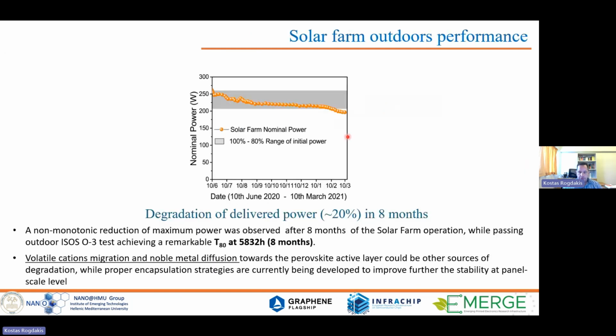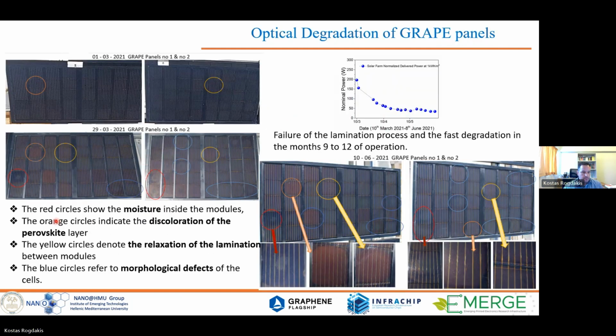But after this period, we recorded some visual degradation effects in our panels. You can see these regions here that are reddish, that correspond to some degradation effects, either coming from moisture or humidity insertion in the panels. And the main problem was the lamination failure around the panels that allowed the penetration of humidity and oxygen in the panels, in the modules, and then in the cells, destroying some of the cells and the modules.